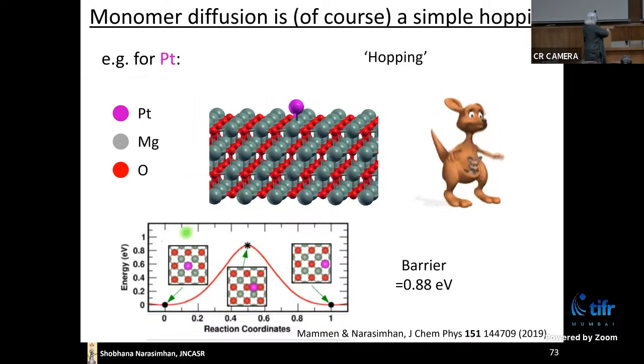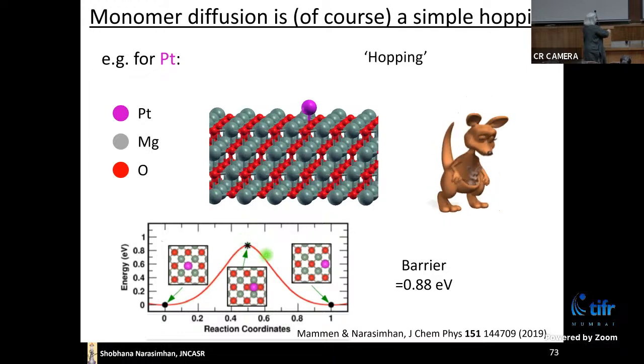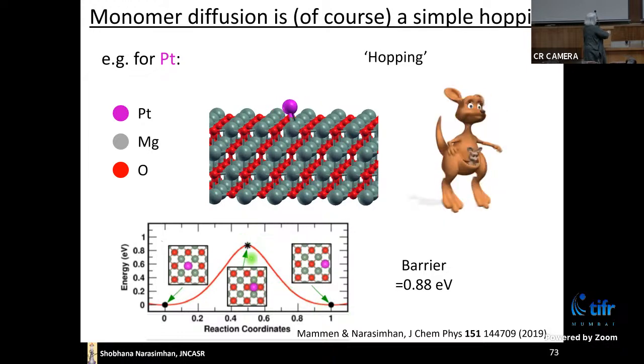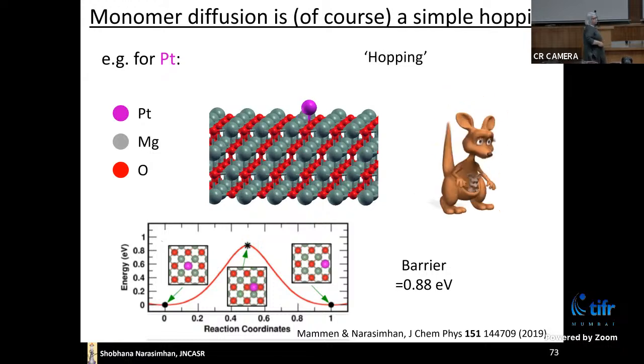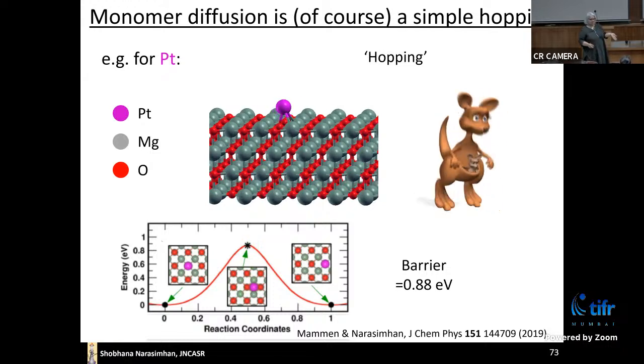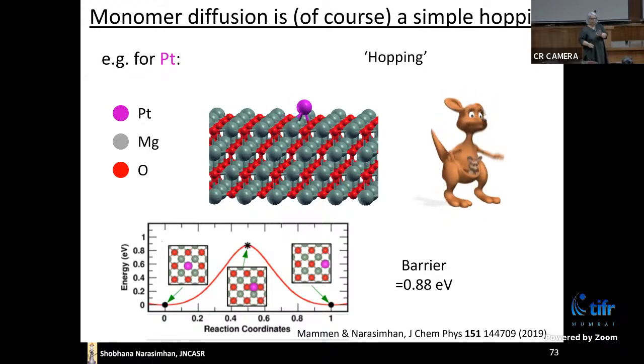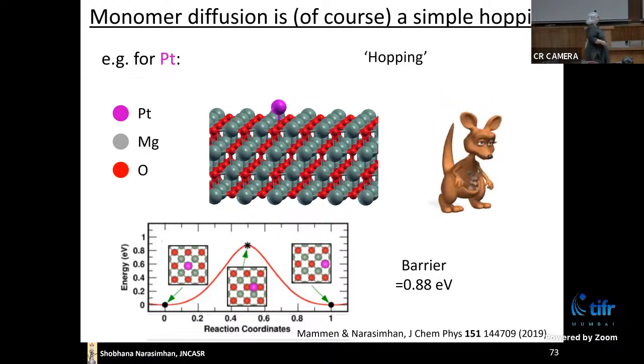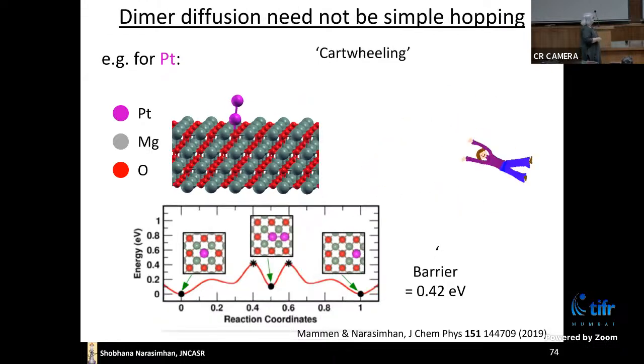This lower graph here shows you how the energy changes along the process. So this height here is the barrier, the diffusion barrier, the energy you have to supply for the atom to move. Okay, nothing too exciting here. The first surprise comes when you look at two atoms, a dimer, a nanoparticle formed of two atoms. And what you see is that it doesn't just translate along. It does this cartwheeling motion. Okay? And the barrier is significantly lowered.